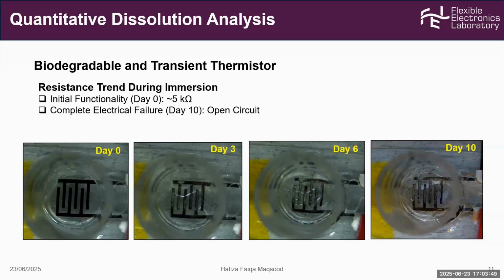And then with the passage of time, the material degradation was measured. It was clearly seen that the material starts to dissolve. And on day 10, the sensor showed complete electrical failure. Its resistance was approaching 100 mega-ohm, indicating an open circuit.